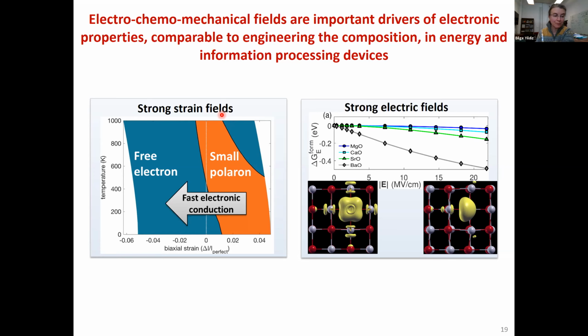We are thinking about that. So you're right, the understanding is in its early stage. For example, the plot here was as a function of just biaxial strain, the simplest type of strain we can introduce in a device. But is this the most optimal strain for us to very strongly stabilize one type of defect versus the other? That would need more coupling, not really hypothesis-driven research, but coupling to data and machine learning, for example, to inverse design the optimal strain tensor. The strain tensor could be any complex direction that would give the most ideal outcome, but we don't know that yet, right? So we're in this process of understanding the coupling of strain and electric fields to these outcomes, but we are considering next, especially in the context of strain, to couple the DFT calculations with machine learning algorithms to give us the best strain tensors with the most optimal ionic or electronic outcomes.